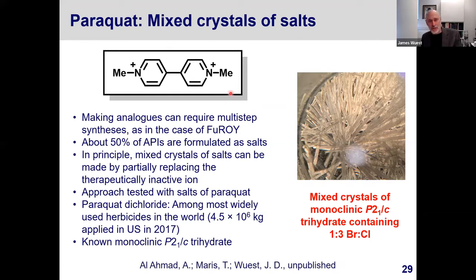And we've tested that with paraquat. Paraquat dichloride turns out to be one of the most widely used herbicides in the world. And even in the US in 2017, about 4 million kilos of this compound were used as a herbicide. There are different crystal forms. So there's an anhydrous chloride, there's a dihydrate, but there's a standard monoclinic P2(1)/c trihydrate form.